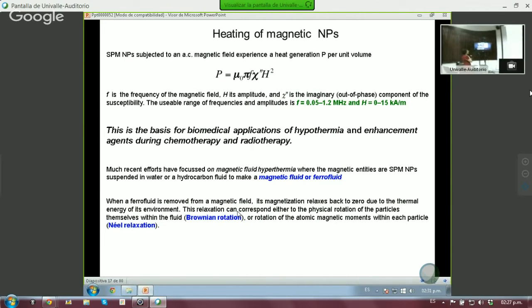And in a way, what you have here are the frequencies, which could change. What we have to always remember is that the range of frequencies and amplitude tolerable by a human body is: the frequency should be about 0.05 to 1.2 megahertz, and the field should be about 0 to 15 kiloamps per meter. Anyway, this is the basis for biomedical application of hyperthermia and the enhancement agents during chemotherapy and radiotherapy.